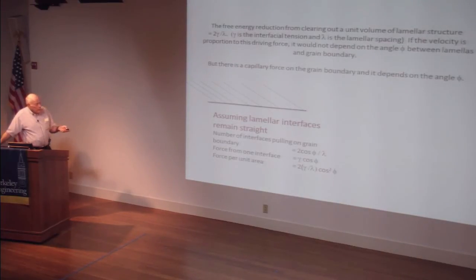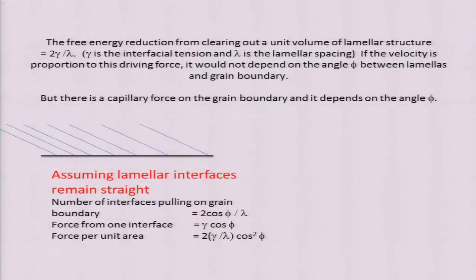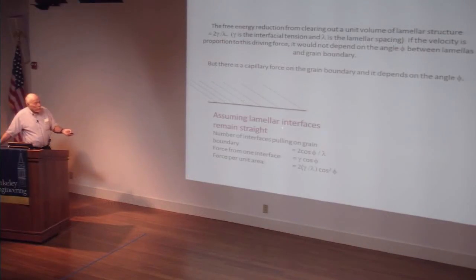So here is, assuming the lamellar interfaces remain straight, there's this angle phi between a boundary and so it's moving up in this direction, being pulled by these. So the boundary has 2 cosine phi over lambda, and the force from the interface is this. That's also cosine. So we have a cosine squared from here. Whereas if we just, that cosine squared would not be there. It would just be 2 gamma over lambda if we simply dissolved this stuff and turned it into something with no lamella. So the general driving force is isotropic, but when we look at the pulling of it.